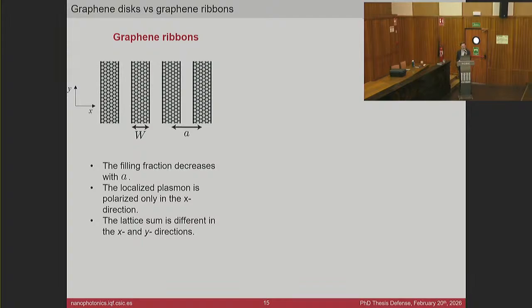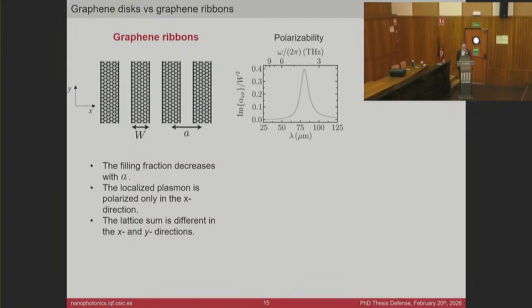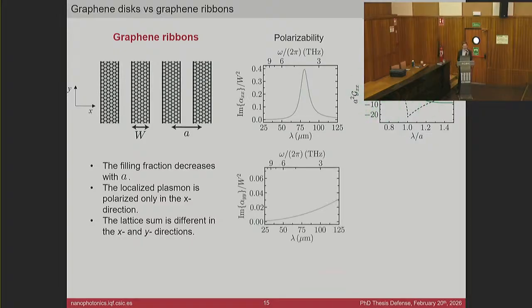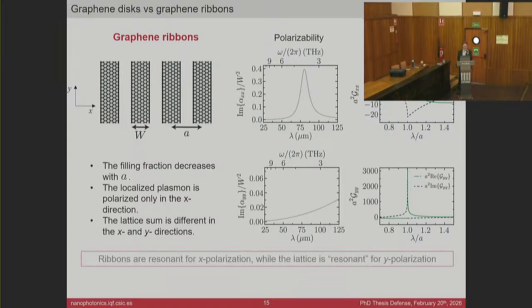Let me show to you. If we plot the polarizability of the ribbon in the x direction, we can see a nice particle plasmon. However, the lattice sum in this direction doesn't diverge, and thus it doesn't attain large values. On the other hand, in the orthogonal direction, the y direction, since the ribbon is ideally infinitely extended in this direction, it doesn't become resonant, and we can only see some dispersion associated with the conductivity of graphene. However, in this direction, the lattice is actually resonant, and it diverges. So we have a problem, because we have ribbons that are resonant in one direction and a lattice that is resonant in the other direction.